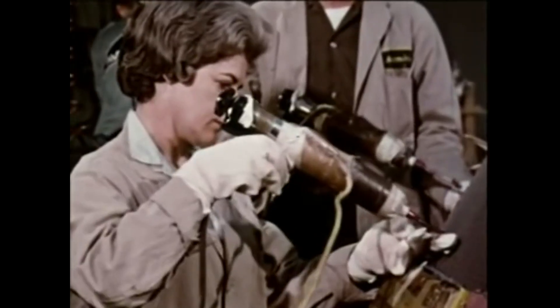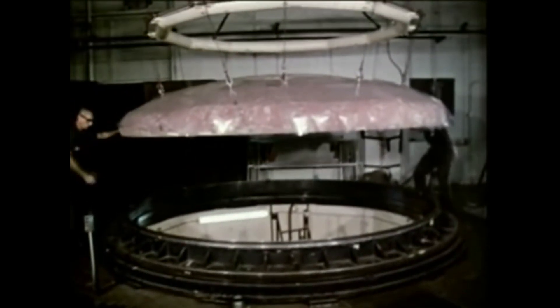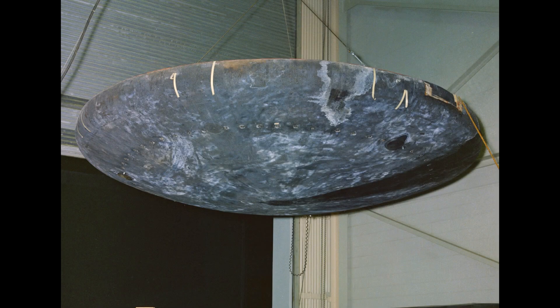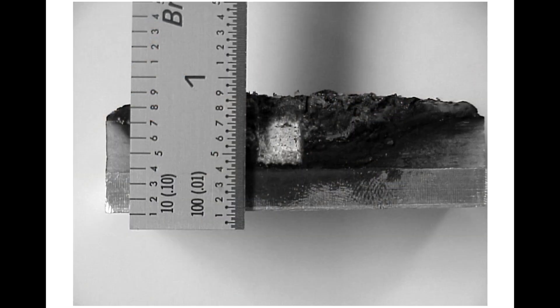You might imagine that a heat shield largely made of plastic would melt and flow away, but it's actually a thermosetting plastic, meaning the polymers are essentially interlinked and wound together, so that instead of melting and reforming it literally just starts to break down chemically. As it gets heated, various gases start to be evolved: water, methane, carbon dioxide, carbon monoxide — but what's left behind is a significant amount of carbon, so it literally turns black. The low-density carbon left behind is an incredibly good insulator that further protects the material beneath it.